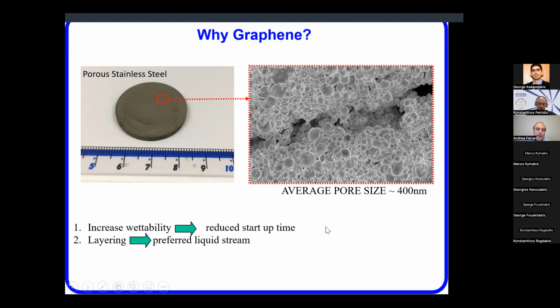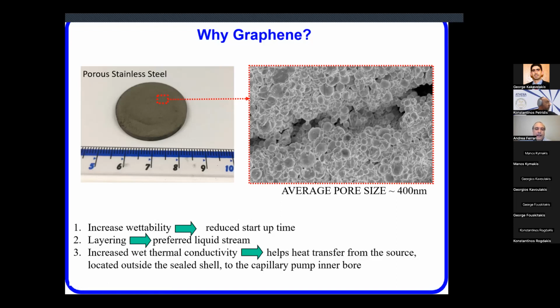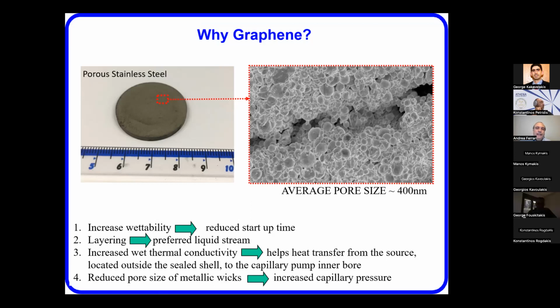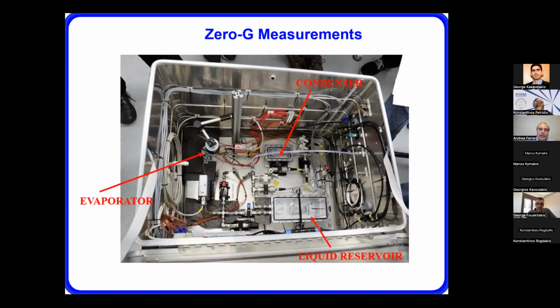The layering creates a preferred liquid stream, and the increased wet thermal conductivity helps transfer the heat from the source outside the shell to the capillary pump inner bore. And also it does reduce the size of the pores, which again results in increased capillary pressure. So prototypes were created. This is a very, very early prototype of a few years ago. Now, I don't have time to go into the most recent one, but this was tested in zero gravity experiments.